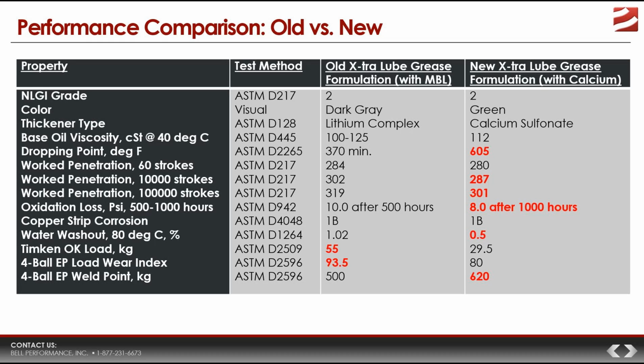So what they do is run it for 500 hours or 1,000 hours, and measure any change in PSI, any pressure change. Looking at the difference in test results between the old grease and the new grease, you see a significant difference. The old grease lost 10 PSI after 500 hours on the test. The new grease, they doubled the time length to 1,000 hours, and got even less loss, only 8 PSI loss. That's a significant difference, and that's advantage number 3 for the new X-tra Lube grease: better oxidative stability, to go along with better dropping point and better shear stability.